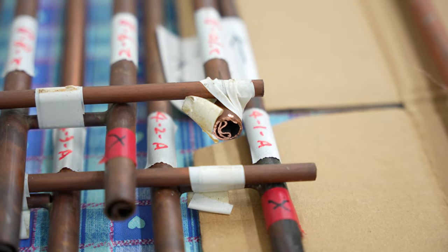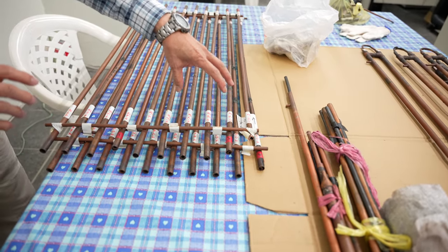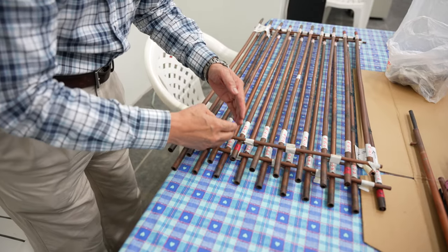Failure. And that means the damage or the failure due to the effect is random — mostly on the core side, but sometimes moves to the other side. From my experience on the mechanical engineering side, it's a kind of flow instability — two-phase flow instability.